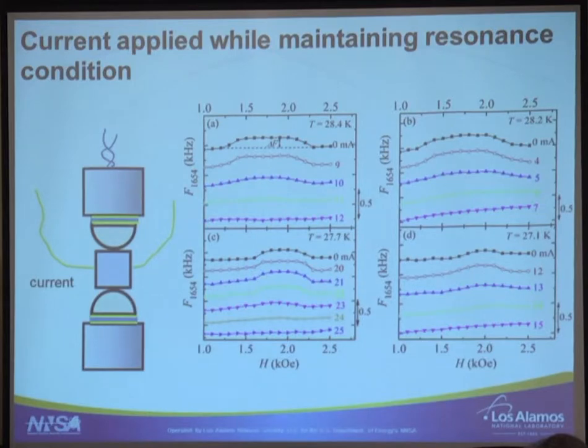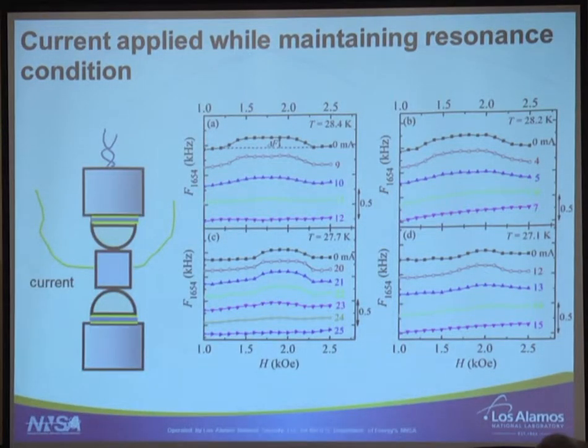Yes and no. So this is a bulk thing. You see a bulk signal. Now, people have measured thin films by making substrates very, very thin, and then, let's say, if you measure changes, you can make some modeling of a two-phase, and you can get the elastic constant of the change. Or you can do just qualitative changes and say, well, I see the change here and can track a phase diagram. Because this is extremely sharp, you can see changes in resonant frequencies to 10 to the minus 9. Because this gets tracked in a resonance, you can see very small changes. So that's really good. So you can do qualitative things.